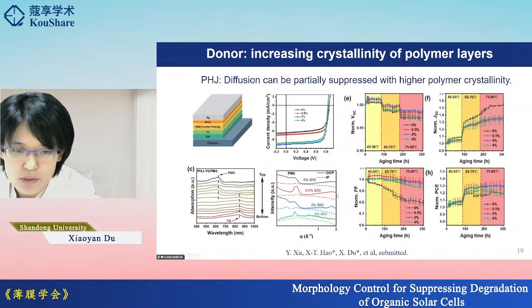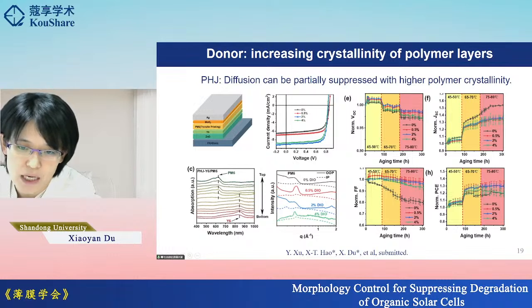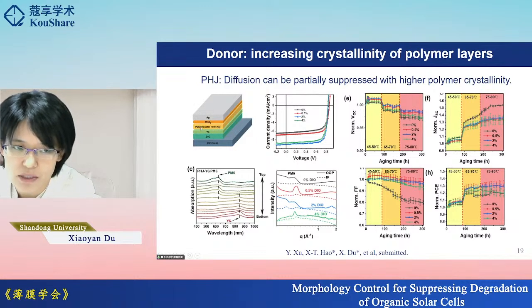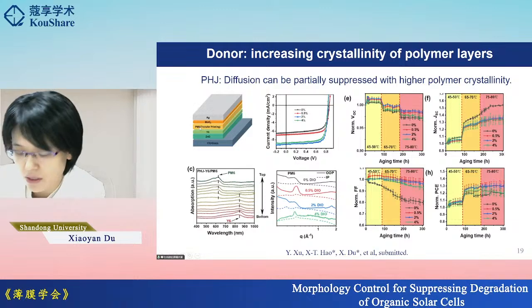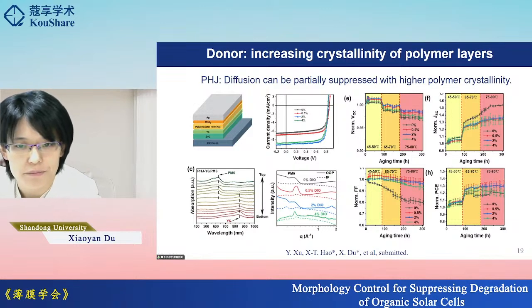If we have more crystalline polymer layers, this degradation in fill factor and the increase in the photocurrent is suppressed, indicating that this interface is more stable. So we can stabilize the interface by increasing the crystallinity of the polymer layers.